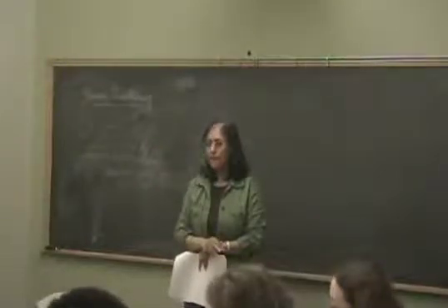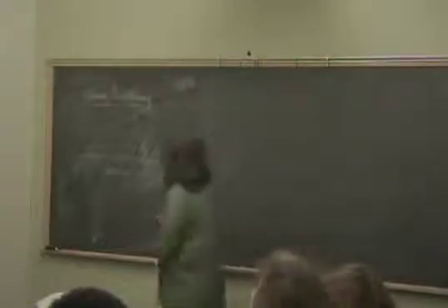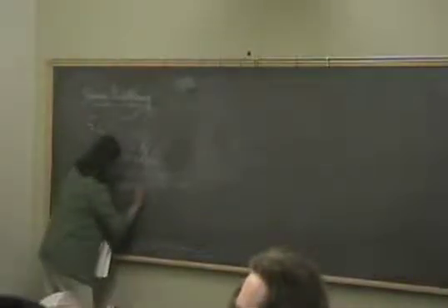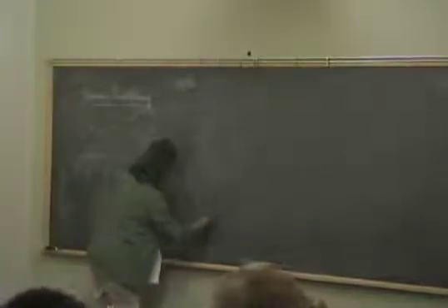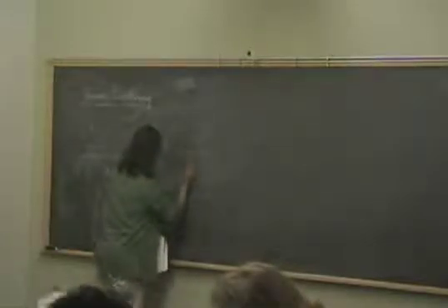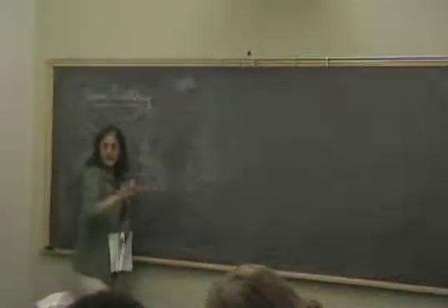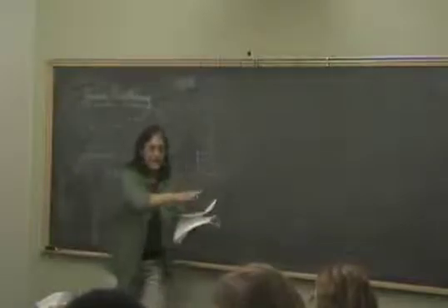It can also be used to see optical phonon spectra. Mainly because here's omega, here's q. You remember we got things like this when we had basis atoms. That's where your layers come in. Suppose you have 2 graphene sheets and they are vibrating in phase, that's an in-phase mode. If they are vibrating out of phase, that's an optic mode.